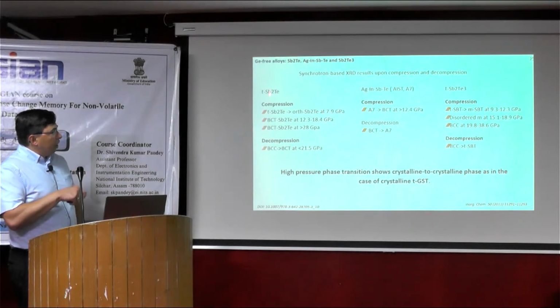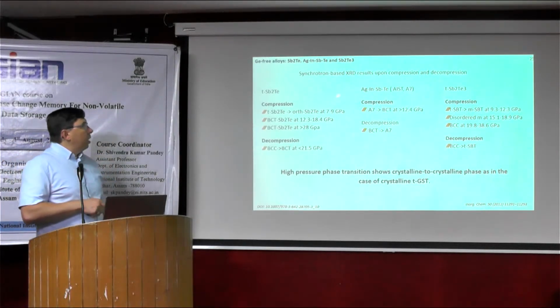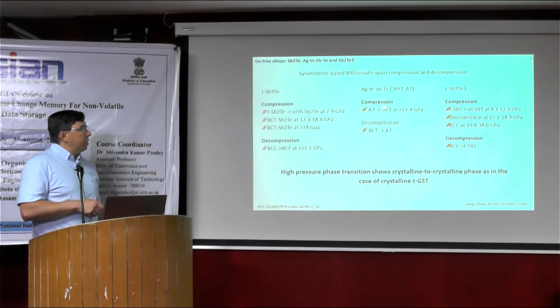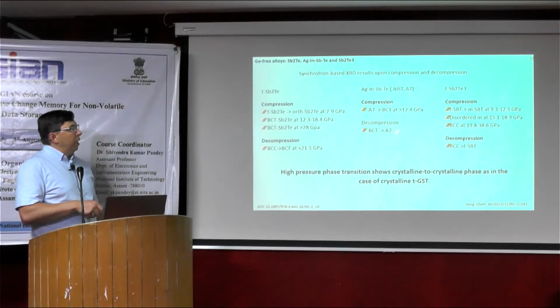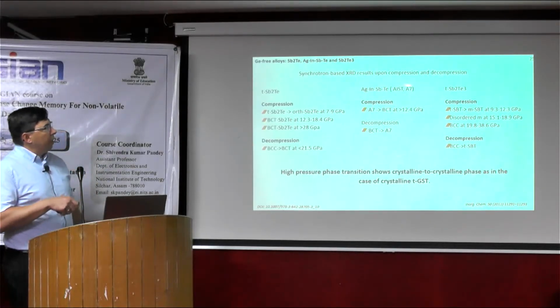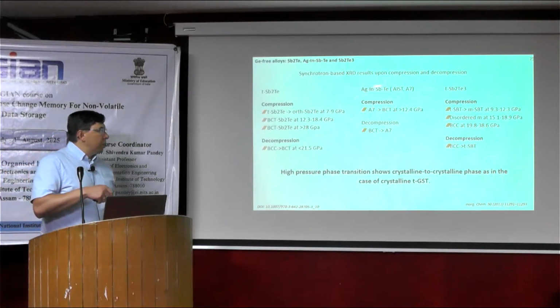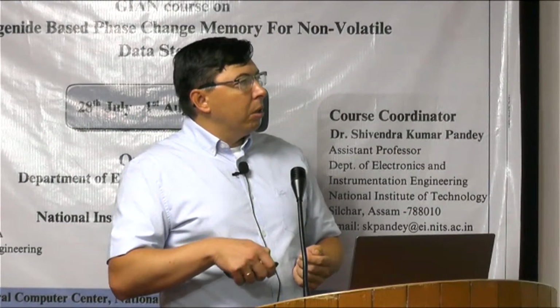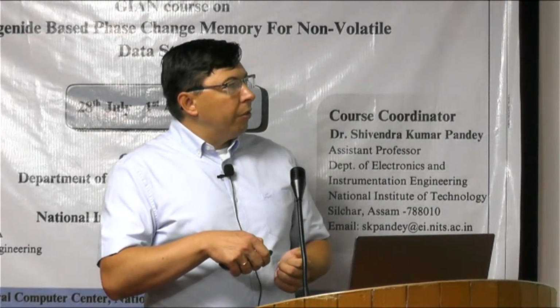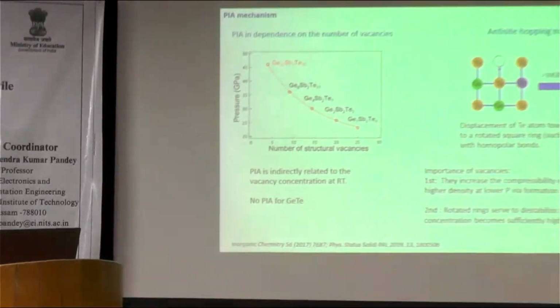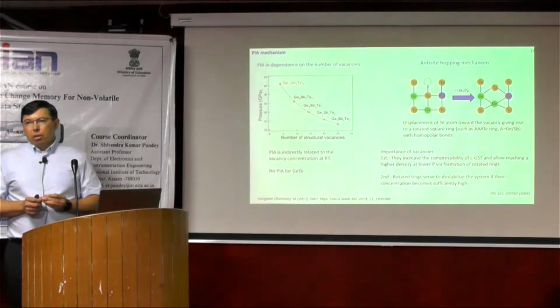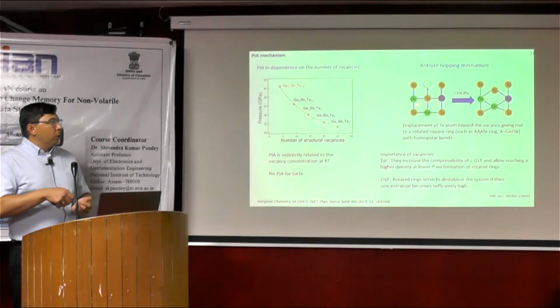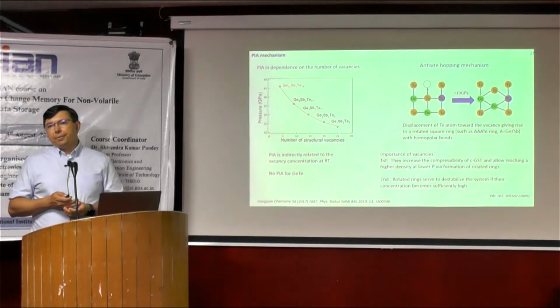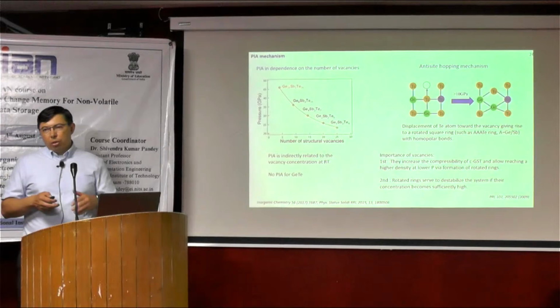So again, here there is a crystalline transition, but there is no memory effect like in the case of the trigonal phase. AIST is transformed from the A7 structure to the BCT, and then BCT back to the A7 structure. So here we see a reversible crystalline process. Then in square-like rings we have formation of some homopolar bonds. And if you have a high amount of such units, then the system just transforms to the amorphous state. So it's based on the atomic movement. But this is one idea of how it can happen.